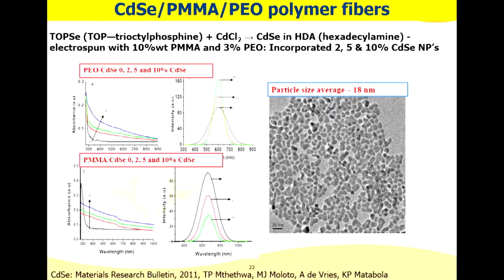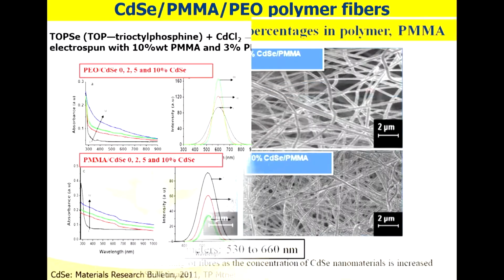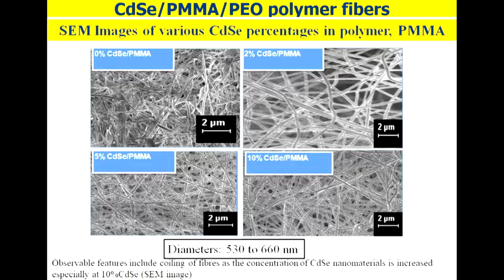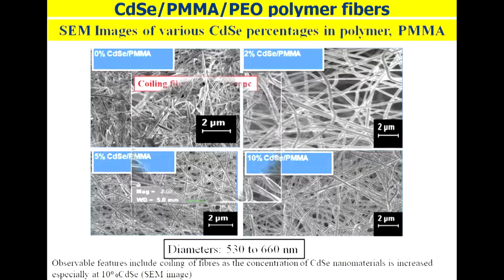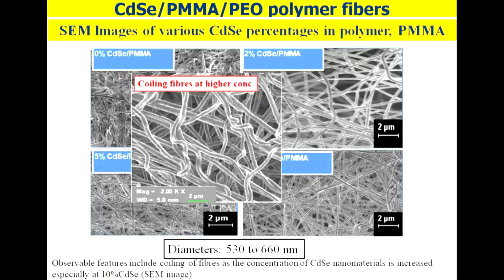The first one that we tried at CSIR was to see if we could take cadmium selenide, prepare it and incorporate it into these two polymers. This is what it looks like, non-spherical particles of CdSe. The moment you start introducing it to your polymers, they start influencing the polymer's diameter, and when you increase it up to the highest amount, you start seeing the PMMA starting to coil and form a helical structure compared to when there's less of it. So it demonstrates that there's some influence of CdSe on the structure of the fiber formation, the diameters thereof.